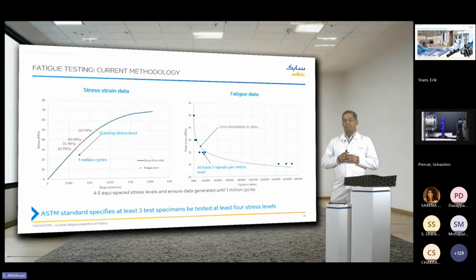At our labs in Bangalore, we follow the ASTM D7791 standard to perform our fatigue tests. We start the fatigue test at around 60 to 70% of the ultimate stress. And for each condition, we perform tests at at least 4 stress levels. At each of these 4 stress levels, we conduct 3 repeats to get an idea of the variability in the data. Now, we typically try to hit 1 million cycles to failure. The outcome of this test is shown in the graph here.